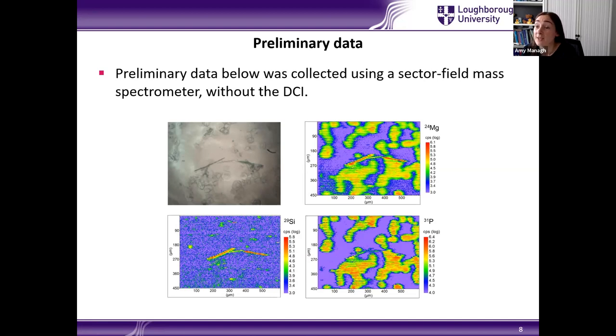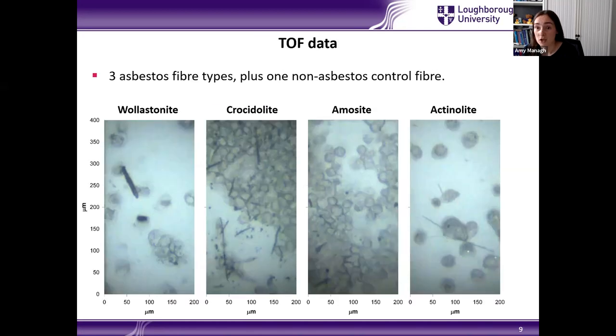The downside that the sector field technology has, though, is that magnetic scanning is very slow. So when you're working with transient signals from laser ablation systems, it's not really the most appropriate technology to use. You can use a fast scan mode, which will allow you to jump quickly between masses using electric scanning. And we were able, as you see here, to measure three different things at once. However, that does come at the expense of a restricted mass range, which meant that we weren't able to measure elements like calcium and iron, which are actually really important to measure within these fibers. So we realized quite quickly that we would have to switch to using time of flight technology in order to pseudo-simultaneously measure many different elements.